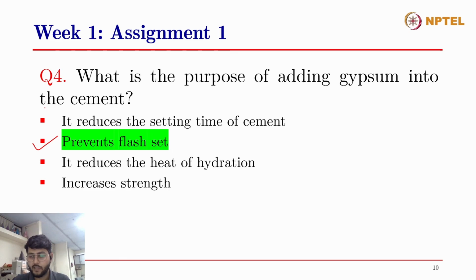So adding gypsum, what does it do? It forms a layer around these aluminates and prevents them from reacting too fast, and also takes part in the reaction between the aluminates and water. Instead of directly reacting with the water, aluminates react with gypsum and water to produce ettringite. Ettringite has a lower volume than hydrogarnets, and it takes time for all the aluminates to react with gypsum and water, and therefore adding gypsum increases the open time of this cement and concrete and prevents flash setting.